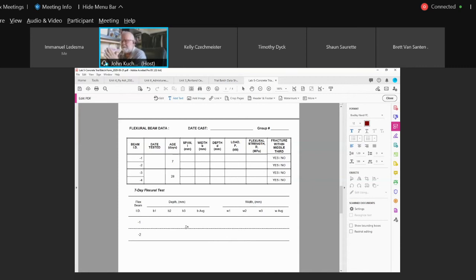But look at the mechanics. Follow the CSA procedures. Okay, you've got access now to the CSA procedures because you can go through the library link. When you test a concrete cylinder, you just don't put it in the machine and bang, load it. The rate that you load that cylinder is very important. If the machine loads it too fast, you're going to get a higher break. You're going to get a higher stress. If you load it too slow, okay, your strength is going to be very, very low. So the rate of loading is very important.